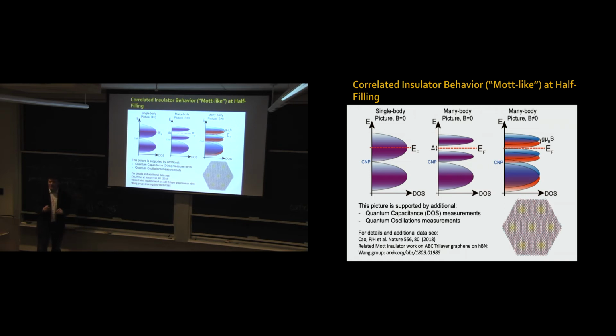Now, this is something that happens not only for graphene on graphene. There are a number of other systems by now that have been investigated that exhibit similar physics. There are a number of moiré superlattices that you can fabricate, and in particular, the group of Feng Wang put something called ABC trilayer graphene on hexagonal boron nitride. It also forms a moiré superlattice, and they reported similar Mott insulator-like states at half filling of their bands, and they posted the paper shortly after ours.